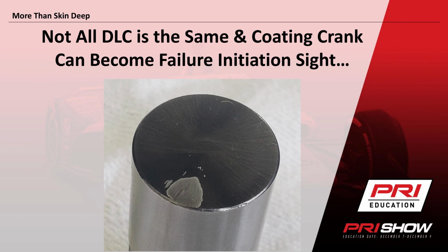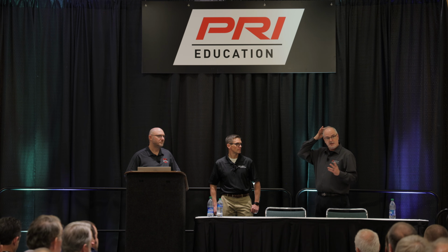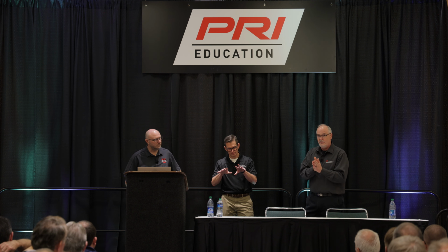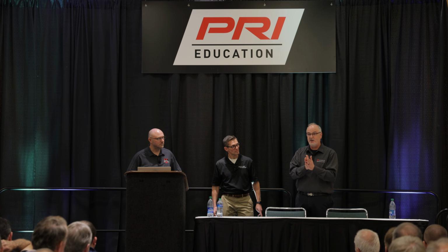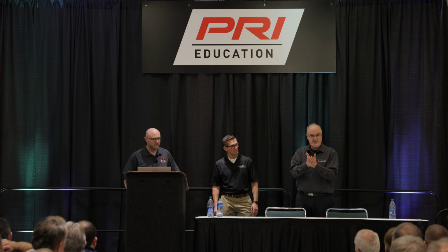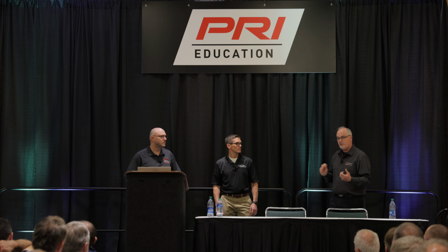You wind up with these really high-end maraging steels that have been nitrided to try to get up close to that 1,000 Vickers, and they put like a 1,500 Vickers layer of titanium nitride before they put DLC, and they put a DLC 3 before they do a 4, to try to get that hardness to be a spectrum instead of a step. But one thing, once you start cracking a DLC, because this goes back to our surfaces thing, when you crack a DLC, what do you think that does to the steel underneath it? You're putting a stress in it. You're giving it a place, just like a razor blade, to start a crack. So you get a crack in a DLC, it's going to transfer into your metal. So you've got to be really careful with your coatings.